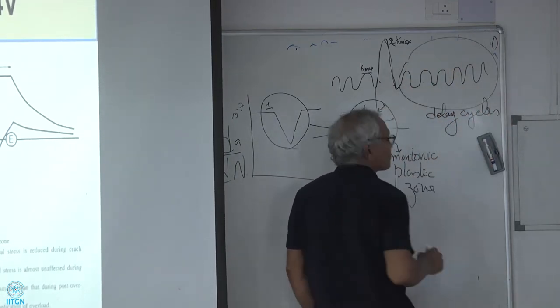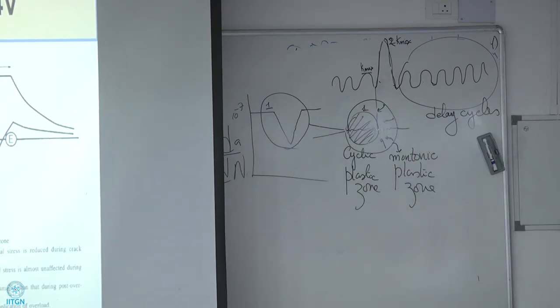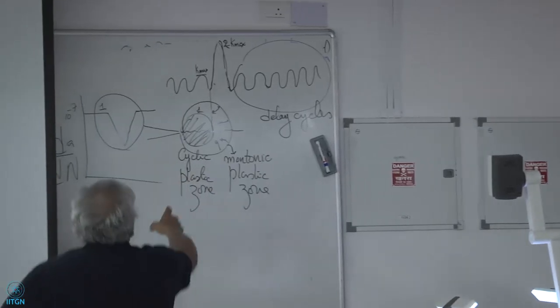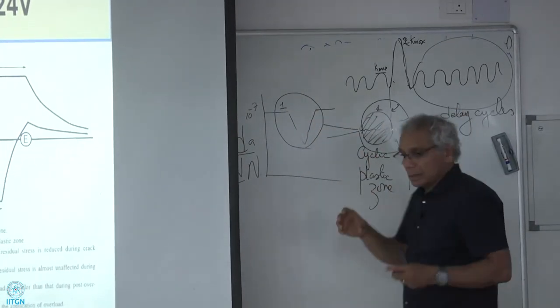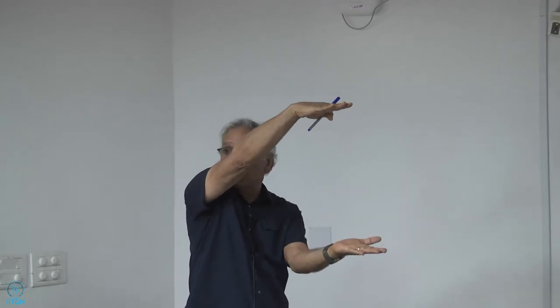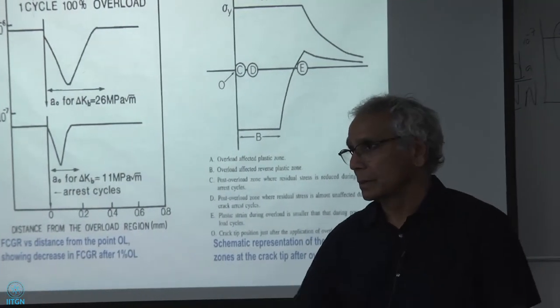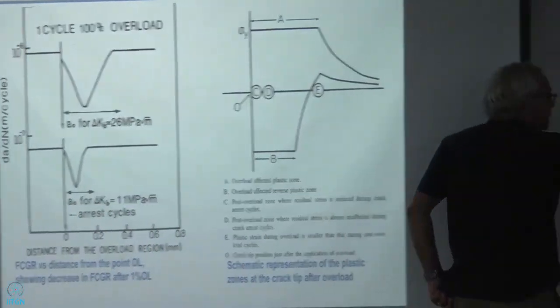You said concentration gradient. True. If I have a little volume element here, this d epsilon that will take place in this volume element will be taking place because of a stress gradient, sigma 2, sigma 1, inside a small zone inside that component. So instead of a concentration gradient, the vacancies are being driven by a stress-assisted diffusion, right? Remember Fick's law, law number one and law number two. The first one is what you just said, diffusion due to concentration gradient. And the second one could be a stress-assisted diffusion.